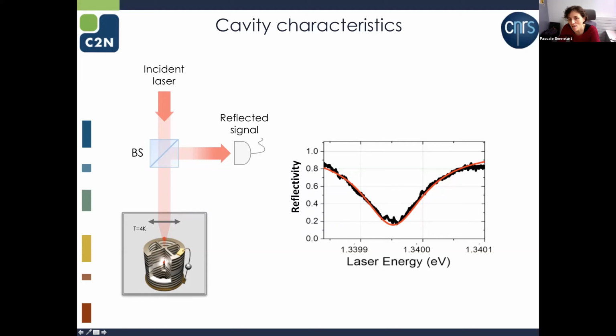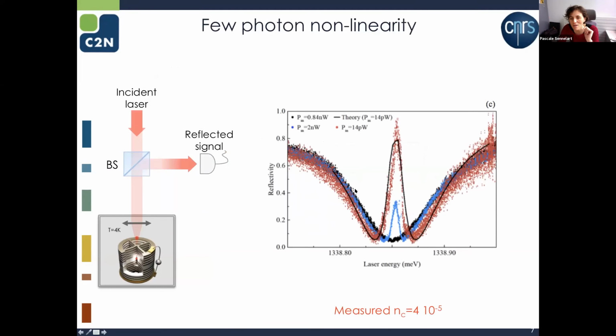I'm scanning the laser and I see the dip of the cavity. So right now, there is no quantum dot in it, no atom. But I have this knob, which is the electric field, and I can bring the quantum dot in resonance with the cavity. And when I do that, I don't have just this dip anymore. I now have a dip and a huge peak here. And this peak here is the atom reflecting the photon. So you see here, I've brought my quantum dot into the cavity, and now it reflects light. And you see here, I have more than 95% reflection just by one atom. So we could think of this as a single atom mirror.